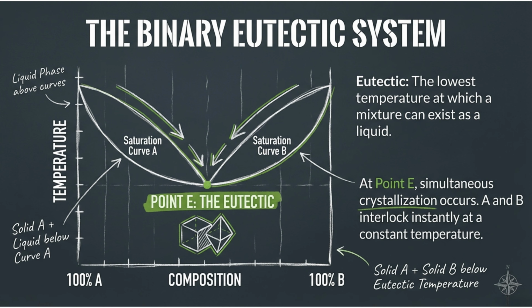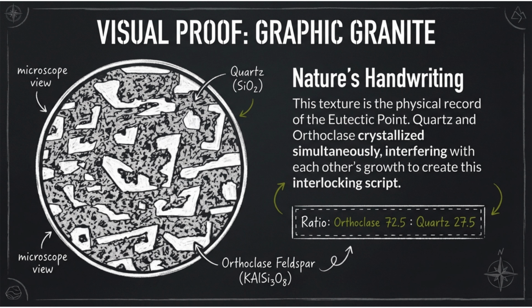This eutectic behavior produces distinctive textures where the two minerals are intimately intergrown, recording their cooperative solidification at a single fixed temperature. Graphic granite provides a beautiful visual record of eutectic crystallization in action. Under the microscope, you see quartz and orthoclase feldspar interlocking in intricate, script-like patterns, almost like ancient writing carved into stone. This texture forms because quartz and orthoclase crystallized simultaneously at the eutectic point, competing for space and interfering with each other's growth. As they grow together, neither mineral can form perfect, uninterrupted crystals. Instead, they generate a complex, interpenetrating mosaic.